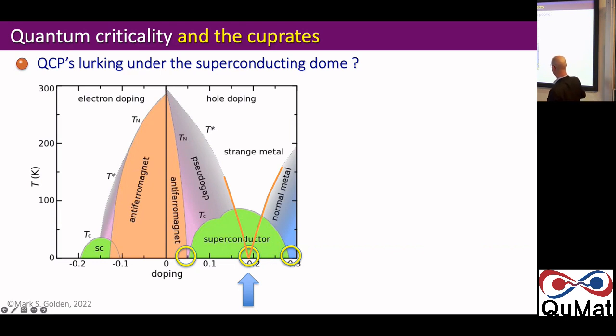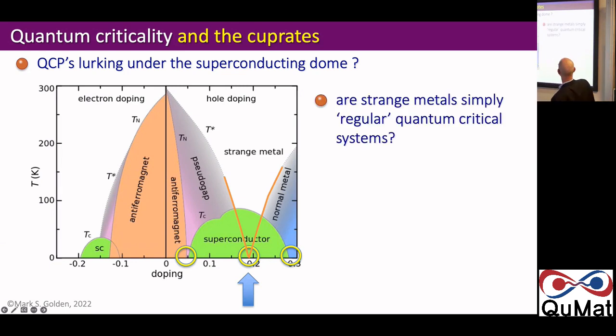We're going from whatever that is to a superconductor. We're going from a superconductor to something which isn't a superconductor. And many people think there is some line, if you take the pseudogap line and this putative line describing a transition towards a more normal Fermi-liquid-like metal, which I don't think is there actually, that there could be a quantum critical point hiding under more or less the maximum TC of these superconductors. And maybe it's this quantum critical stuff which is driving the unconventional superconductivity.